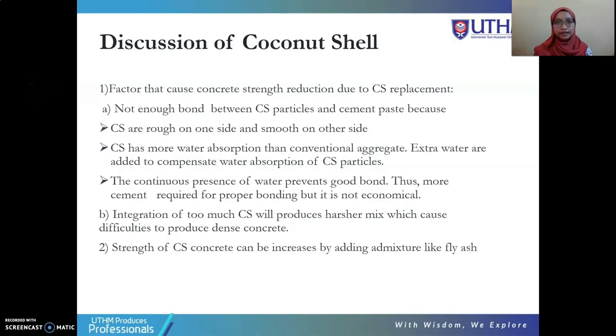There are a few factors that cause concrete strength reduction due to coconut shell replacement as coarse aggregate. First, there is not enough bond between coconut shell particles and cement paste because coconut shell is rough on one side and smooth on the other side. Coconut shell also has more water absorption than conventional aggregates. So, extra water is added to the concrete mix to compensate for the water absorption of coconut shell particles. The continuous presence of water prevents good bond.